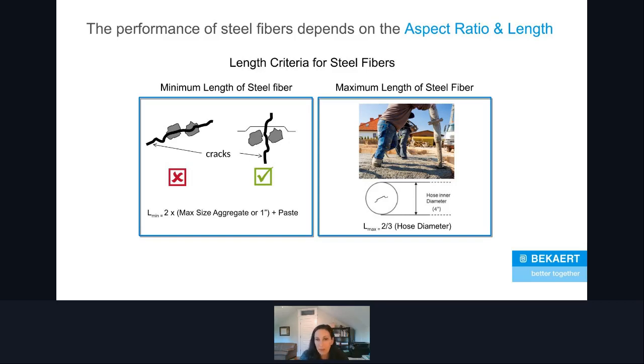On the maximum side, right, I said a moment ago that higher aspect ratio fibers tend to perform better. So why don't we just keep making them longer and longer? And of course, that wouldn't work in practice. There are still cases where folks are going to pump your concrete, and we want to make sure that these are pumpable. So with a 60 millimeter fiber, which is again 2.4 inches long, a 4-inch pump hose would be appropriate. So that's something to be aware of and maybe discuss at a pre-con meeting. Hey, we're using this length fiber. Let's make sure we're not using a 3-inch hose, for example.